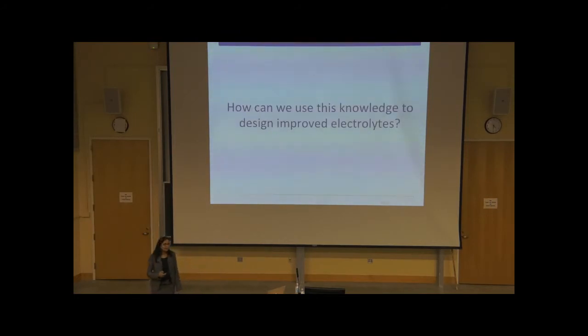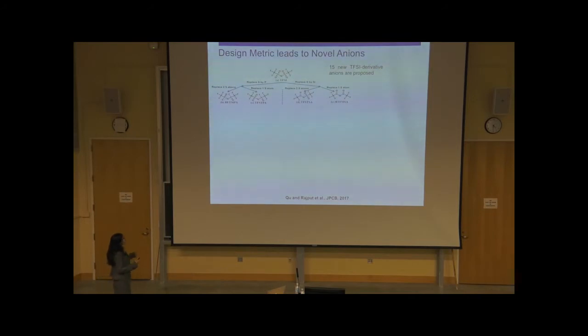But what's important here is what we learned from these systems and how we designed improved electrolytes. So with the understanding that ion pair formation in TFSI might be bad and will lead to decomposition of TFSI by breaking the carbon-sulfur bond, we replaced sulfur with phosphorus and silicon.